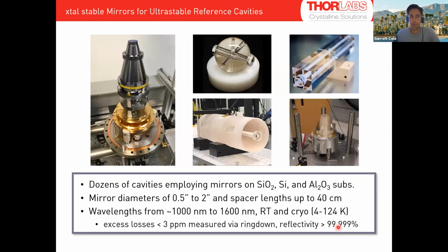So we build these rather complex etalons. Another plug for Crystalline that's helped us with the contacting and polishing and shaping in many of these. Room temperature systems are typically ULE spacers with fused silica end mirrors, and we do cryogenic systems with silicon and sapphire. Typical mirror diameters are 1/2 inch, 1 inch, even up to 2 inch. Spacer lengths are from a few centimeters up to giant ones at 40 centimeters in length. These are usually at wavelengths of 1064, 1550, these standard near infrared wavelengths, with the cryogenic systems going all the way down to liquid helium, 4K.